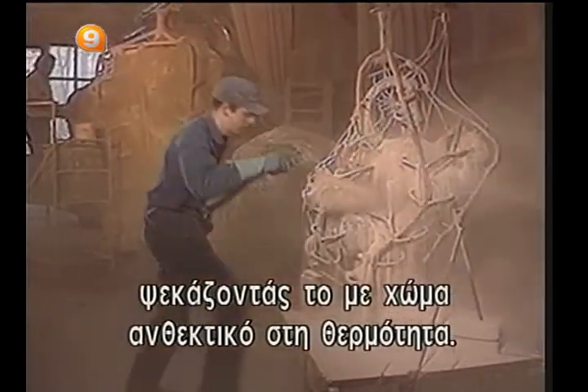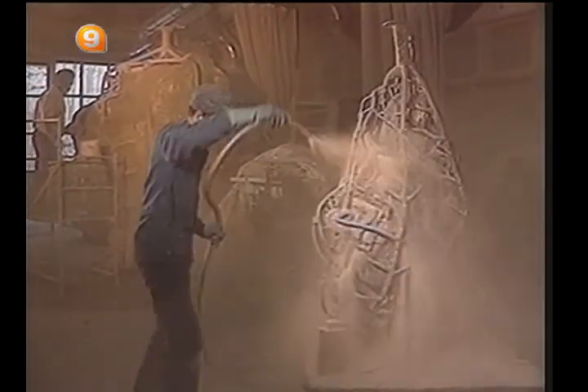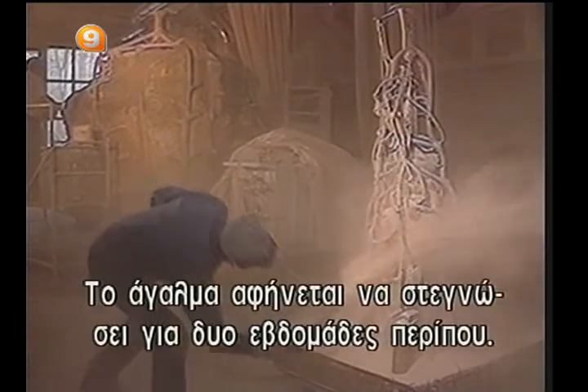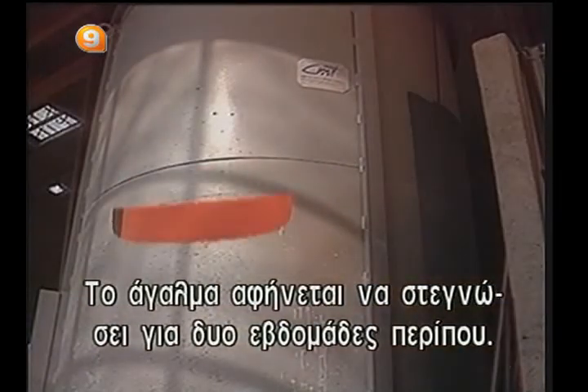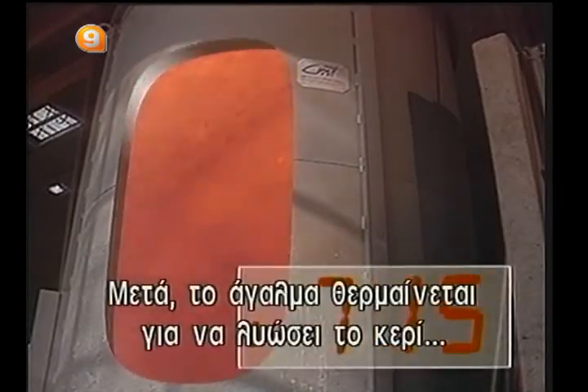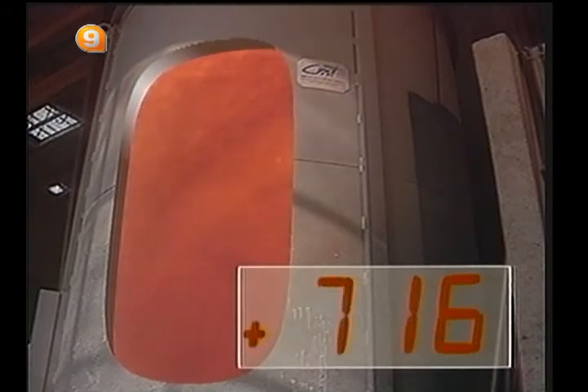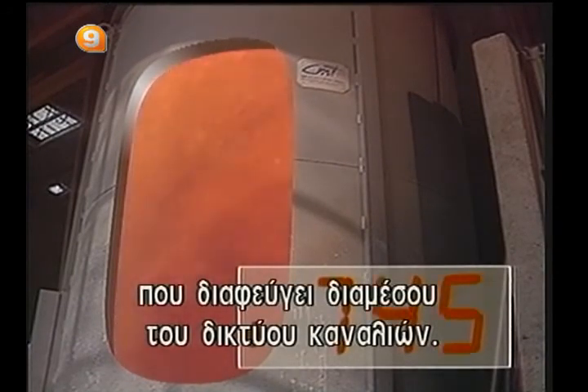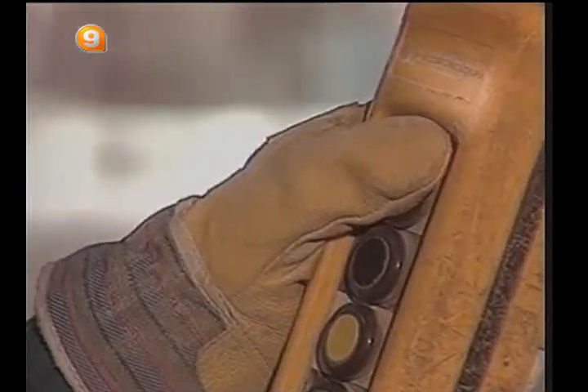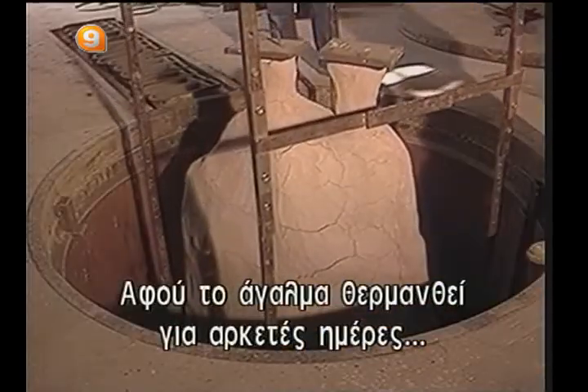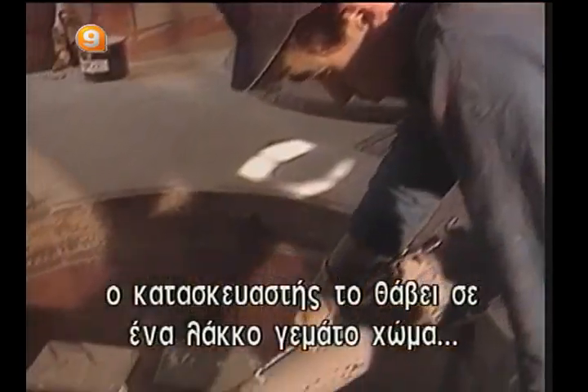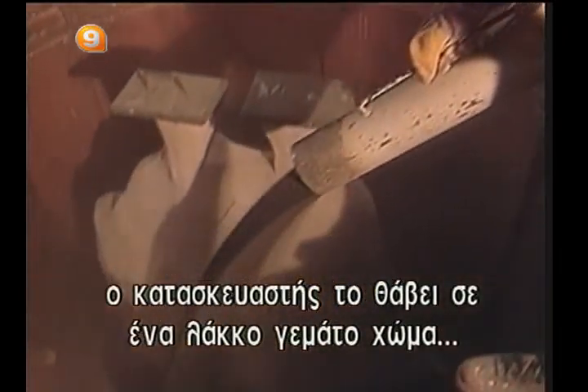He does this by smearing several layers of heat-resistant earth over it. The piece is then left to dry by ventilation for about 2 weeks. The piece is then gradually heated to melt the wax, which escapes through the network of canals. After the piece has been fired for several days, the founder buries it in a pit filled with steel filings or earth.